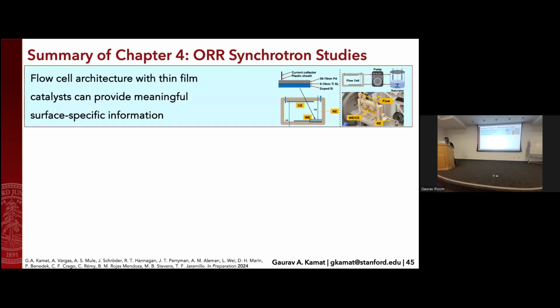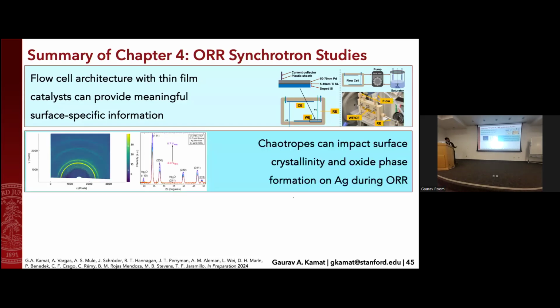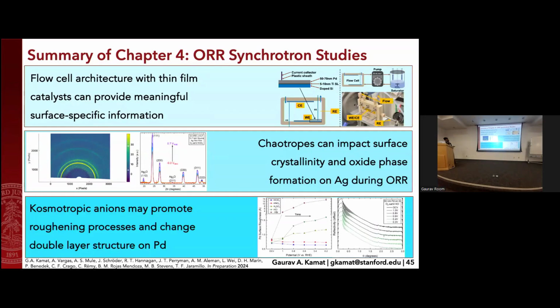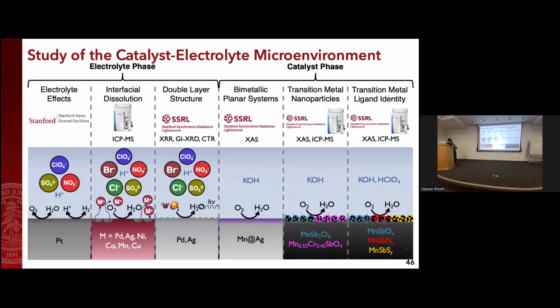So to quickly wrap this up, this flow cell architecture that we used with thin film catalysts can give you a lot of surface-specific information, not just in the two setups that we use, but in a variety of different setups. We saw that chaotropes can impact surface crystallinity and oxide phase formation on silver during the ORR, and that cosmotropic anions may promote roughening processes and change the double layer structure on palladium, whereas those chaotropes really did not. So to wrap it up, this is, again, an overview of everything I talked about.